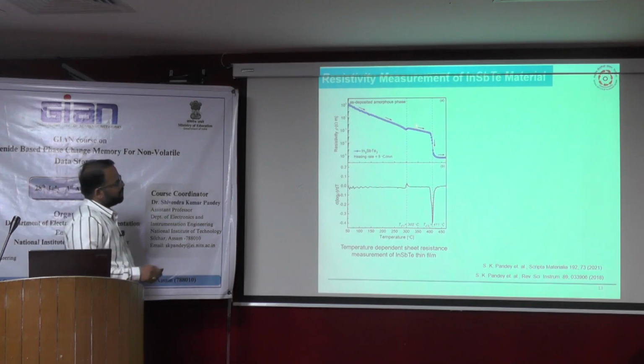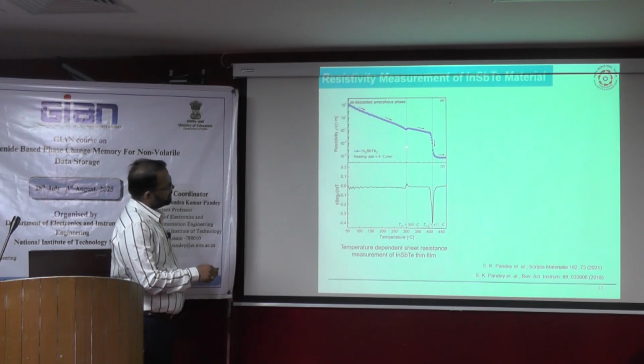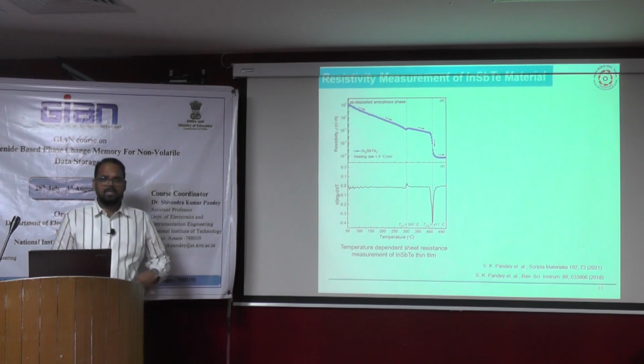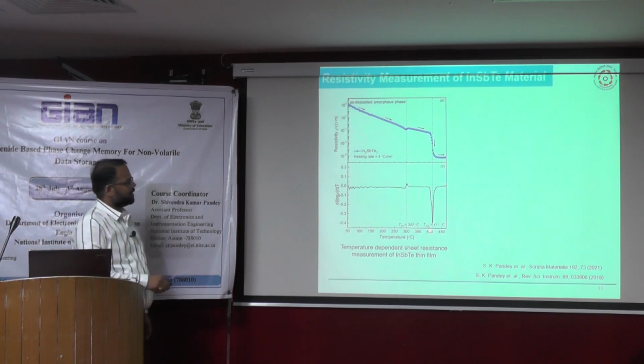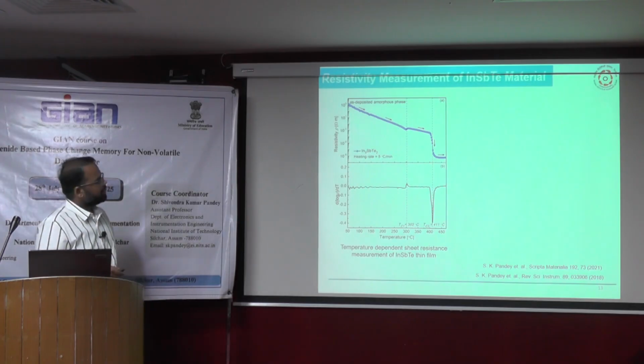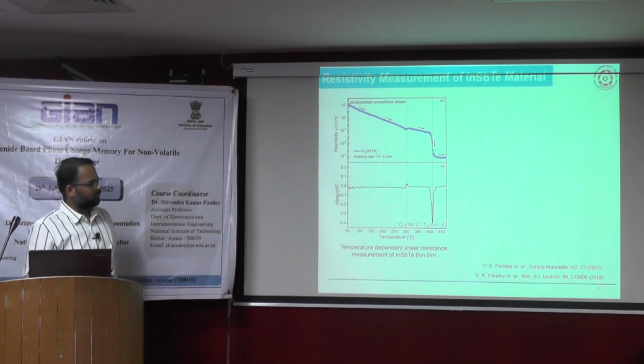It starts crystallizing at 300 degrees Celsius, and at 400 degrees Celsius it is fully crystallized. So this is one step where we can see it could be helpful.